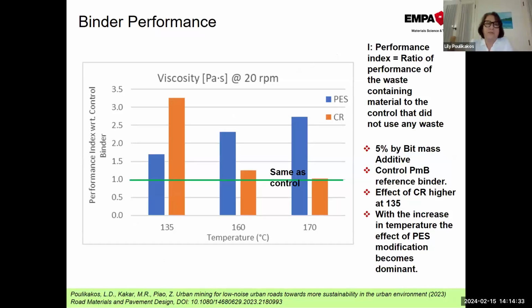We also looked at viscosity. Here we're introducing a performance index, just a simple index that's a ratio of the performance of the waste containing material to the control with no waste. If, for example, the value is 1, that means the performance was exactly the same. And we saw some interesting results. We see the viscosity here with respect to temperature for the polyethylene shown in blue and the crumb rubber shown in orange. We see that there is an increase in comparison to the control in all cases. However, the trend seems to be different with respect to temperature. That was very interesting for us to see, that the results were different.